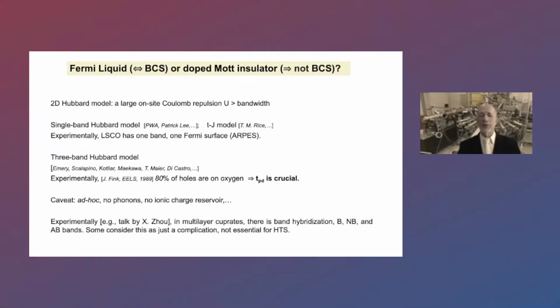The single-band model in its simplest variant has just a square lattice, and you have a hopping integral T, and then you have exchange J, and that's all you have. The experimental support for that is that according to ARPES, in lanthanum strontium cuprate, there is really one band that crosses the Fermi surface, and there is only a single Fermi surface. But then